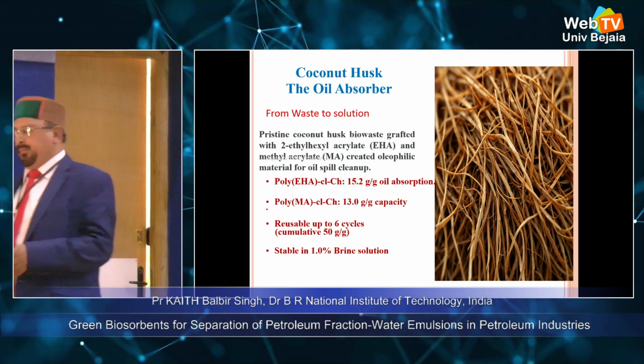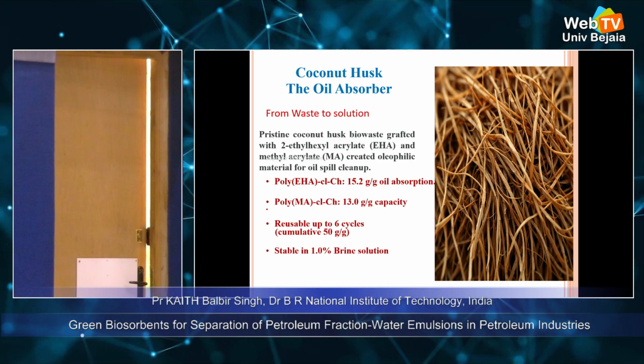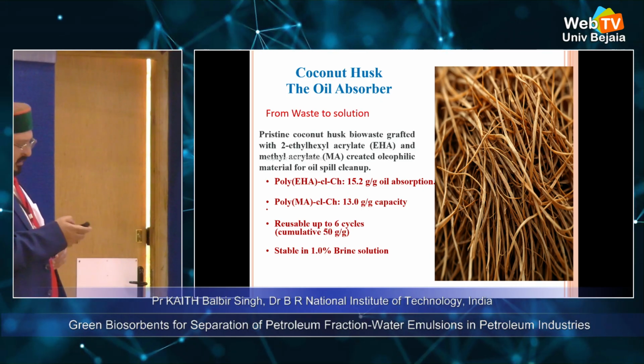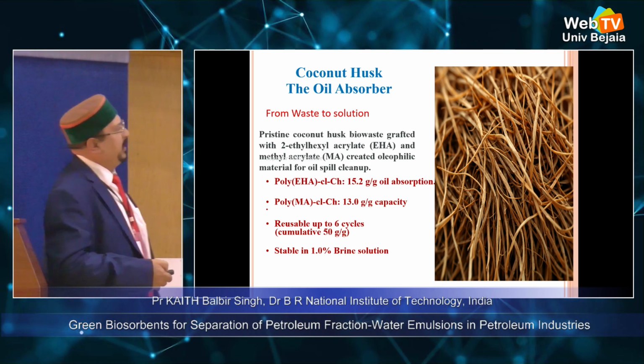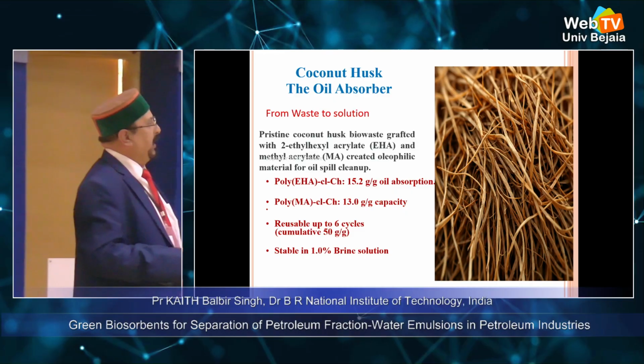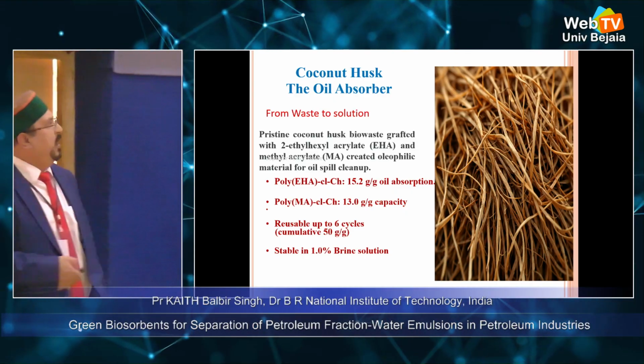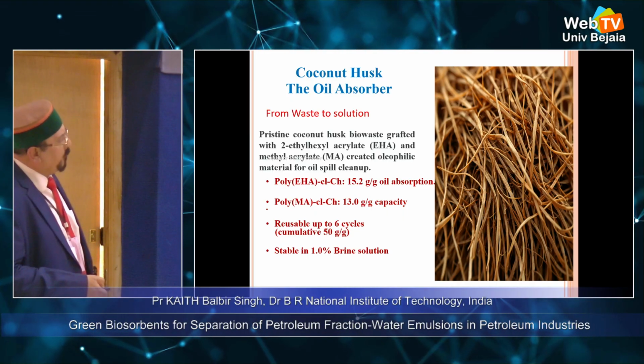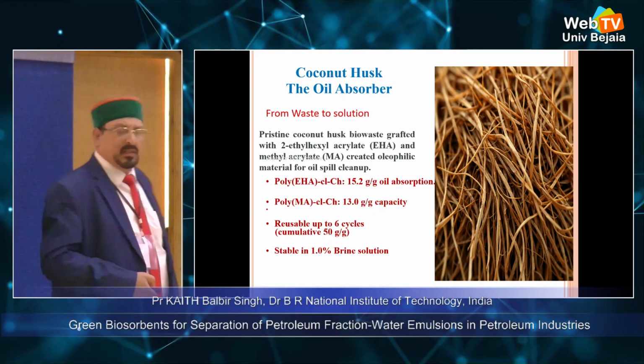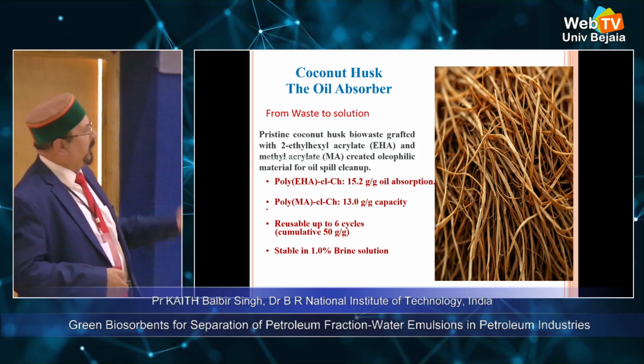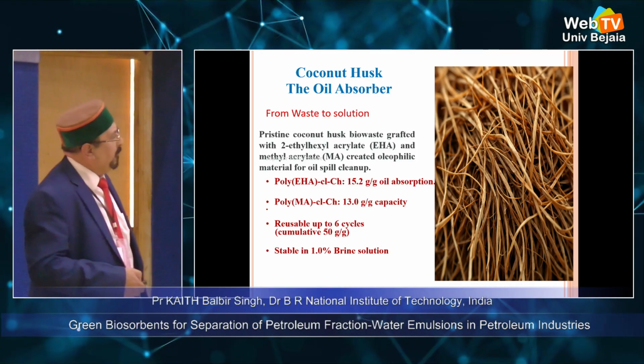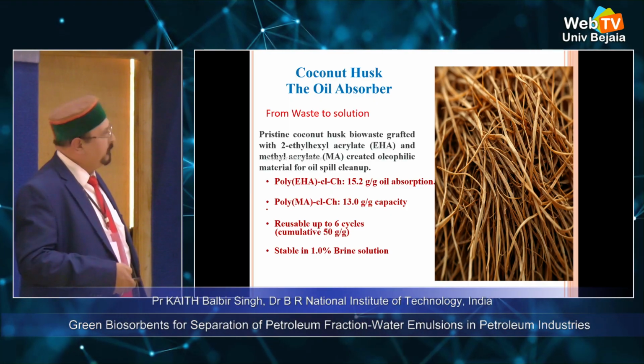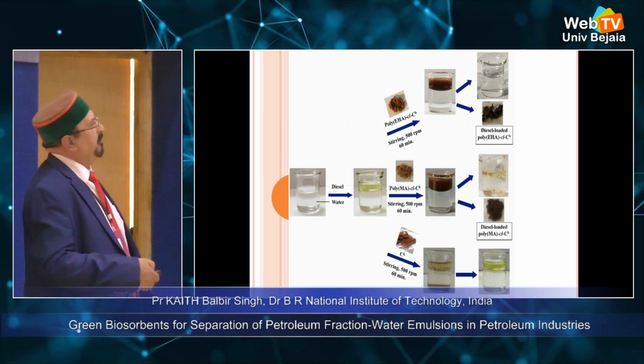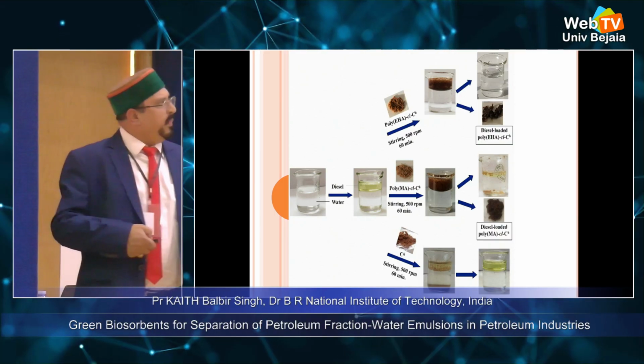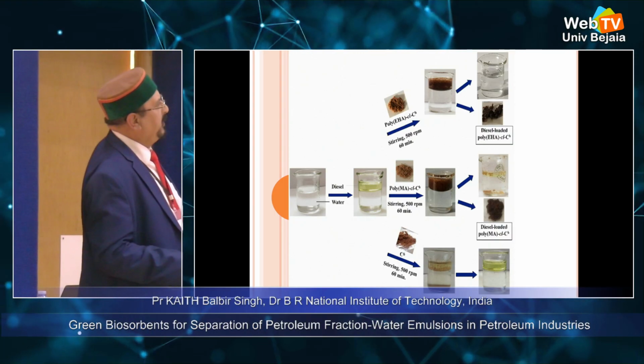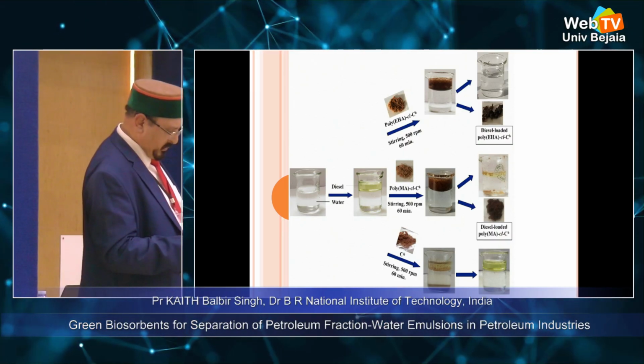At the same time, we prepared hydrophobic materials so that we could use them for the removal of oil spills from the oceans. The materials used here were 2-ethylhexyl acrylate (EHA) and methyl acrylate (MA), grafted over the coconut husk, and we got very good results here. Wonderful results were obtained, and better results were obtained with the grafting of EHA, poly-EHA over the coconut husk, followed by poly(MA) chains over the coconut husk. This was the method used for the separation of diesel water fractions from each other, and we got wonderful results that I will show you here.